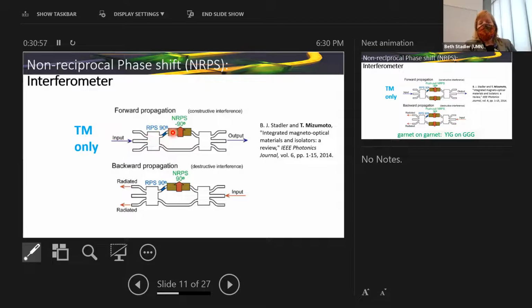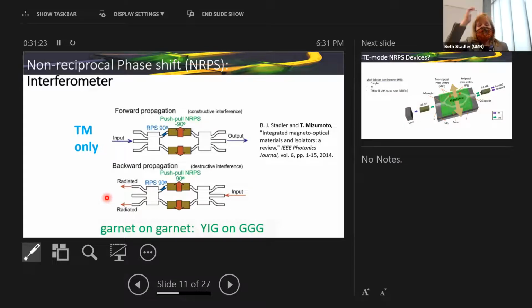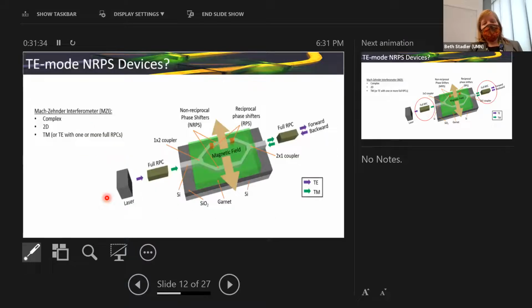You have an input here, you break it into two branches. The key is if you have a reciprocal phase shift of 90 and a non-reciprocal of minus 90, the output looks like it doesn't have any phase shift compared to the other branch. So it constructively couples forward. Destructively backward, because this is non-reciprocal, it's now positive, it adds to the reciprocal, and you get a destructive or this kind of like radiated out the wrong way, light on the way back. And there's ways you can do this, what we call push-pull, where you make the two branches, one has a phase shift forward and the other has a phase shift back. So you can make your device shorter if you have this structure to it.